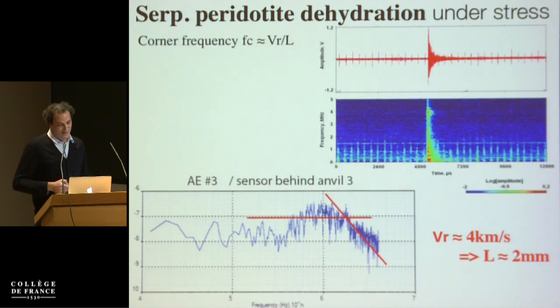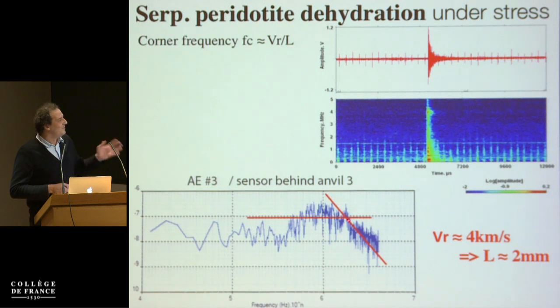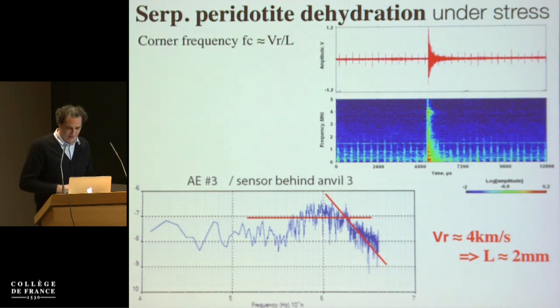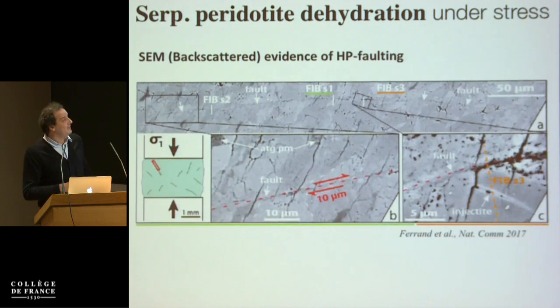If you look at one particular acoustic emission, I'm sorry it looks really not so nice for you all seismologists, but this is the best we can do in a synchrotron environment. So this is a typical spectrum. For the largest one, we have corner frequencies measured by hand like this, around a few megahertz. So for a rupture velocity of 4 kilometers per second, that would give us something around 2 millimeters in size, and that's about the size of a sample. And so we can look if we find faults of 2 millimeters, and the answer is yes.